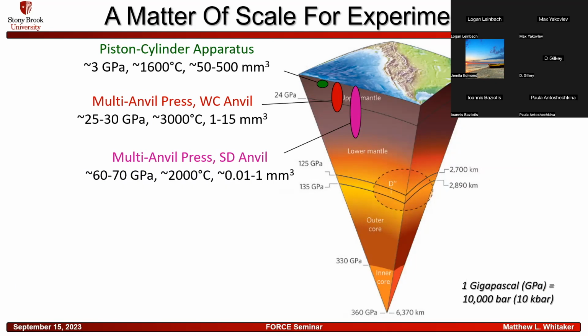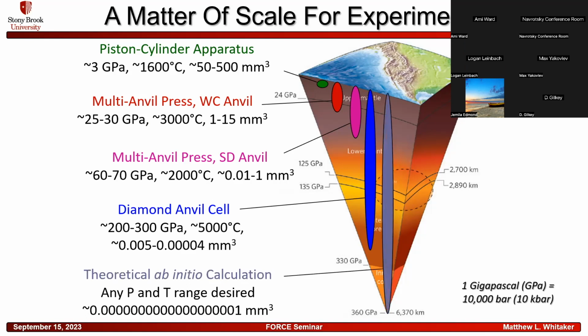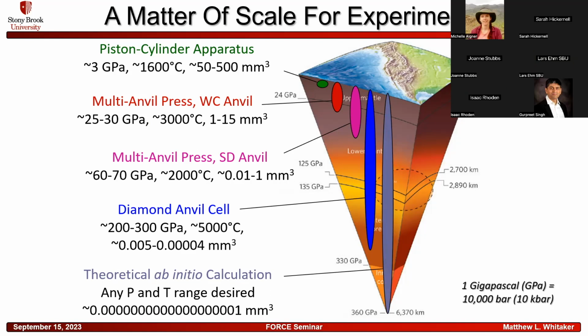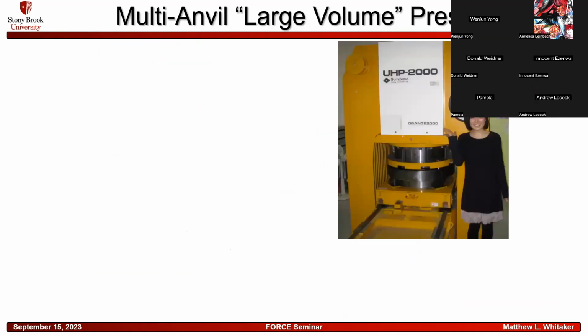And if you use the sintered diamond anvils, you can get more than double the pressure range pretty regularly with a slightly lower temperature and about 10 times smaller sample size. The diamond anvil cell, of course, can go to 200 to 300 GPa without much of a problem, and you can hit temperatures of about 5,000 C, but we're talking about thousandths of the size of a sample that we would have in the multi-anvil. And with theoretical calculations, you can do just about any pressure and temperature range that you desire, but your sample size is on the order of a unit cell, so it's considerably smaller than any of the experimental techniques.